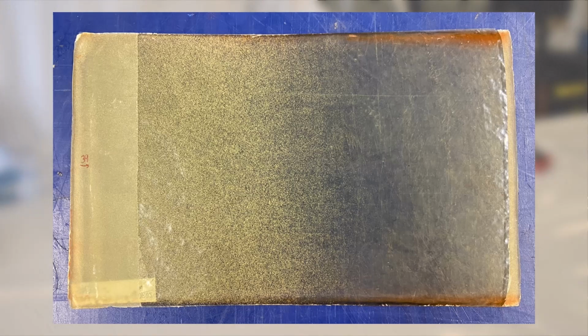On the left-hand side of the panel, the resin flowed very quickly through the first half of the part. Towards the second half of the part, the flow mesh ended and the resin flow slowed. As you can see, the left-hand side of the part is riddled with porosity, whereas the right-hand side of the part has almost no porosity. This relationship between resin flow speed and part quality is crucial to understanding the vacuum infusion process.